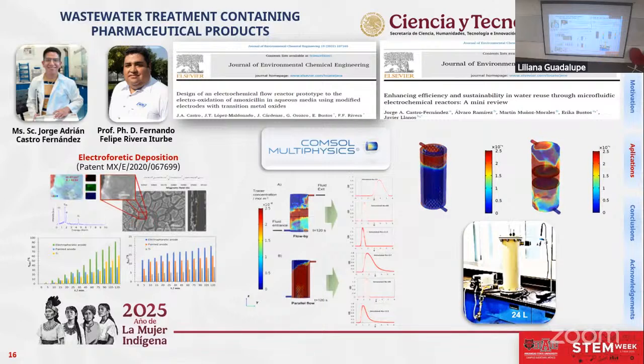The other one shows how we reduce the concentration of the chemical oxygen demand and increase the efficiency when we use the same methodology of electrophoretic deposition in comparison with the painting deposition. This was very important because when you buy electrodes in other countries, usually the technique is painting modification. And we are electrochemists, that's why we use different techniques. In this case, we include this methodology and increase the efficiency.